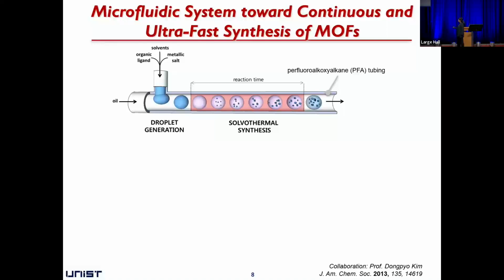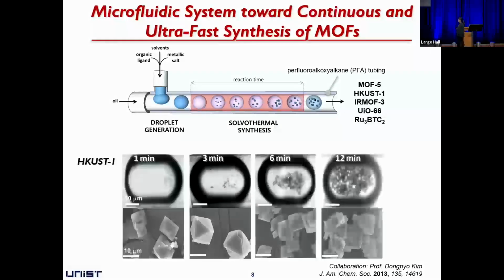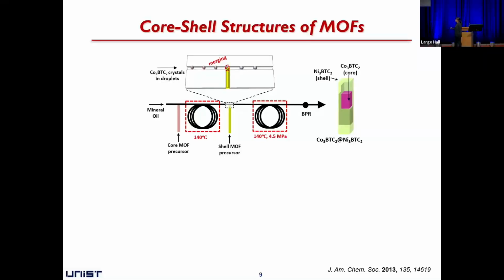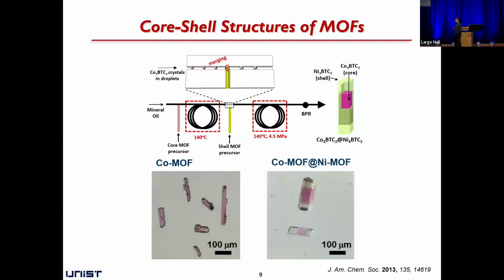As you can see here, we can use PFA tubing, and we can make the background flow with the oil, and we can inject solution of precursors. Then it can make the micro droplet. And each micro droplet can act as a single reaction vessel. So from this system, we could synthesize various types of metal organic framework. For example, in the case of HKUST-1, we can prepare it quantitatively just in 10 minutes, okay, with a very high crystallinity. If we design more smartly, then we also can prepare the core shell structure without workup process.